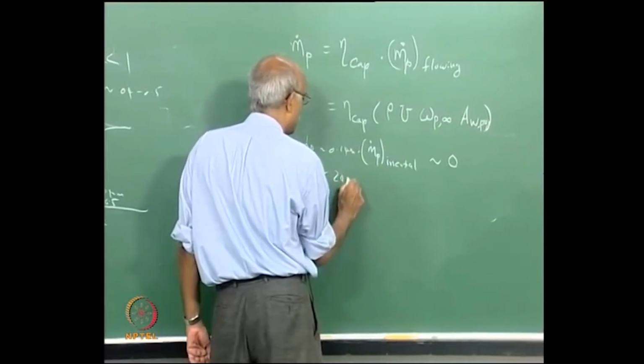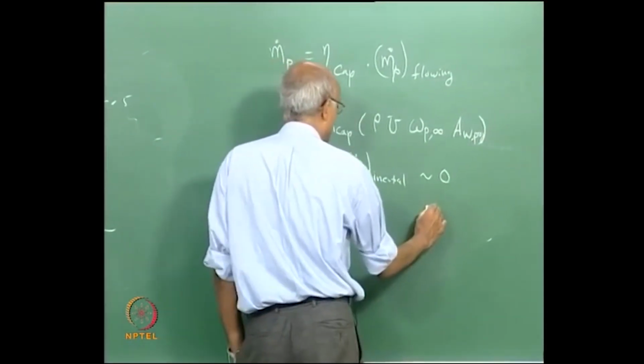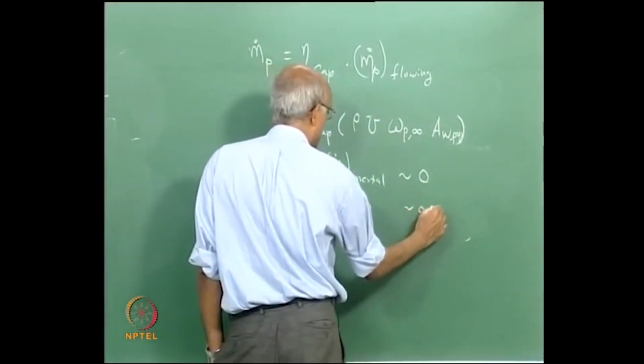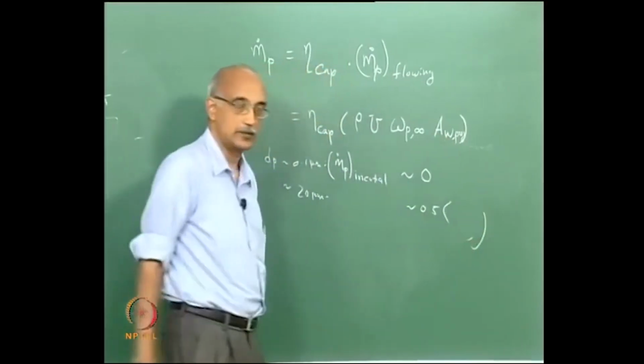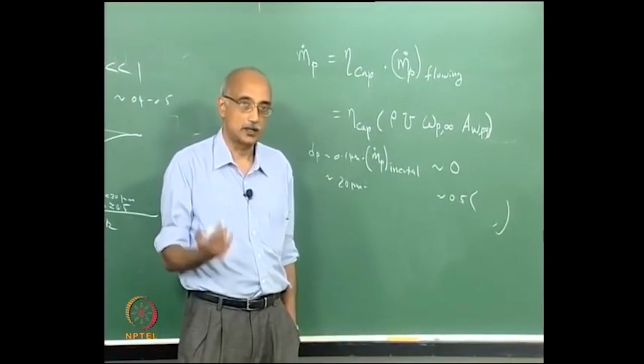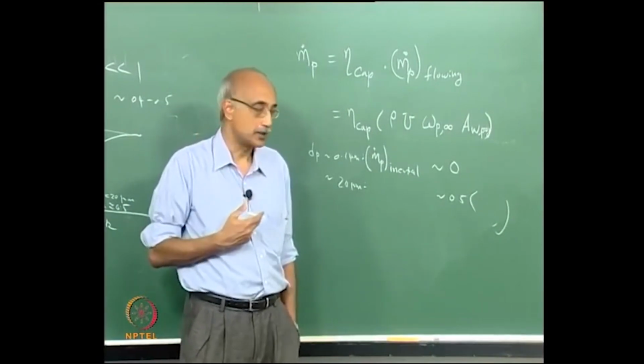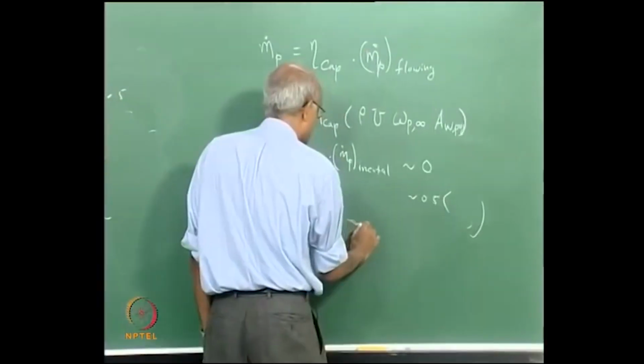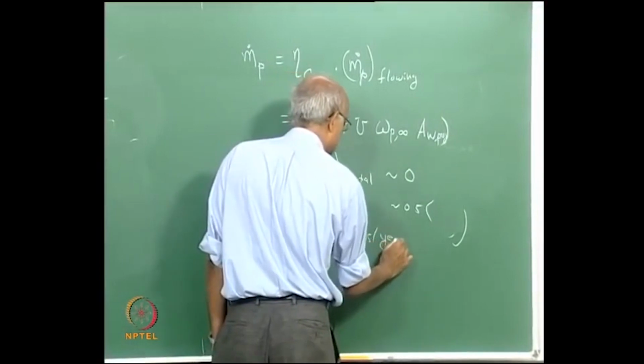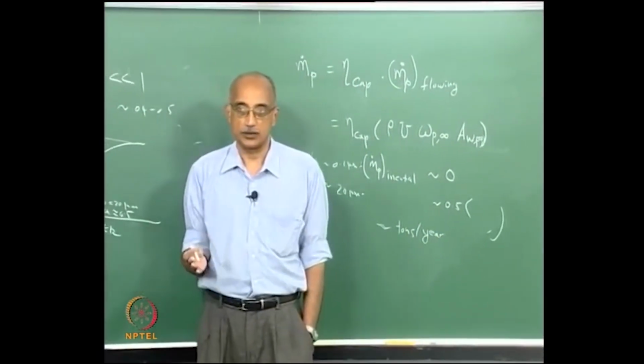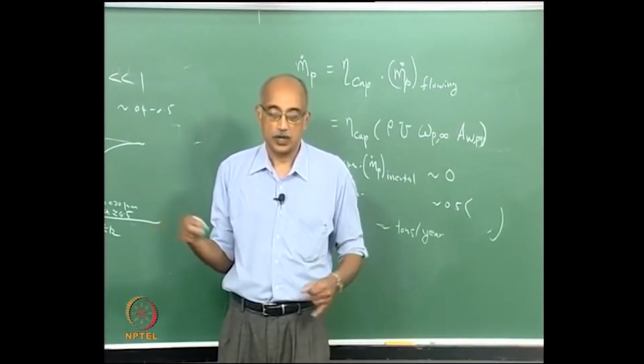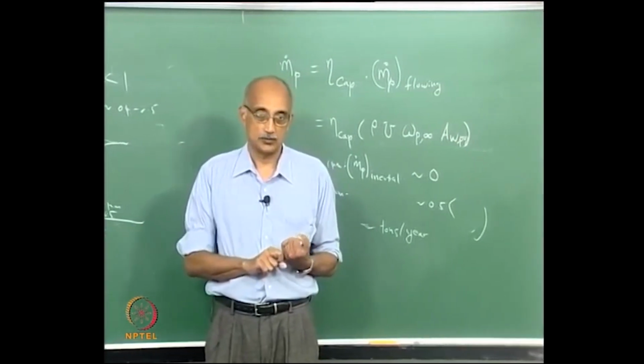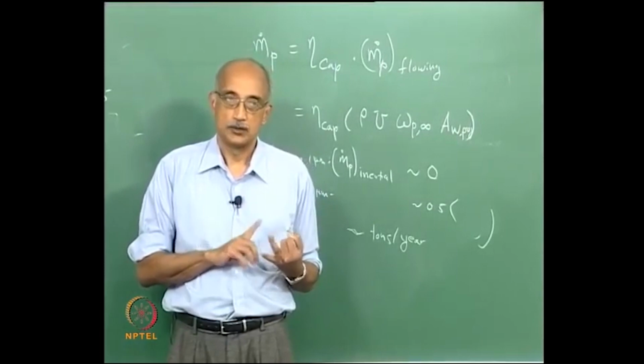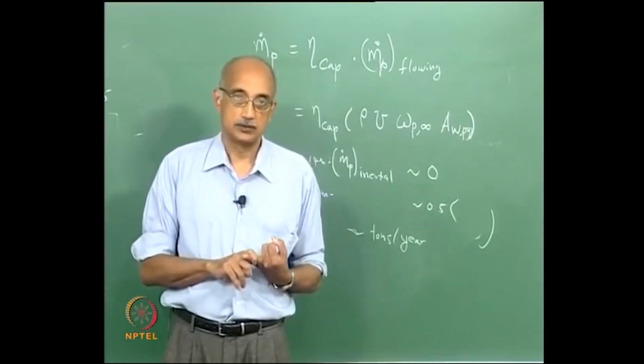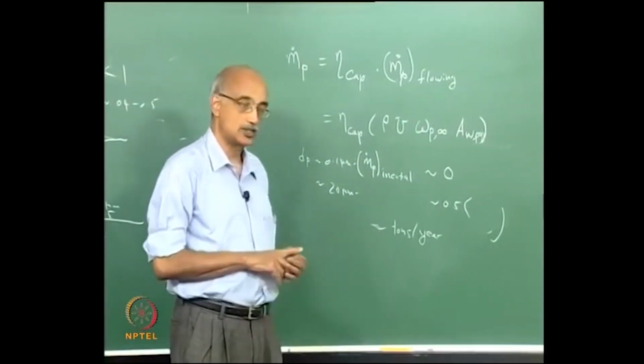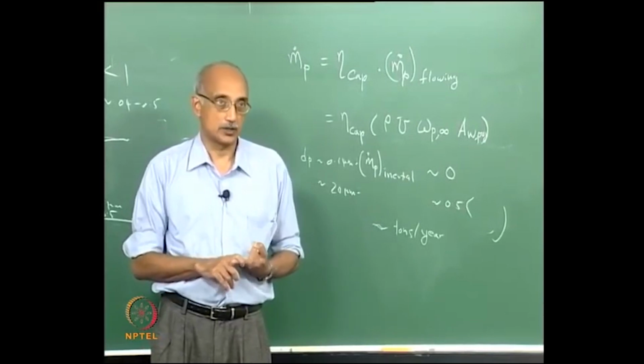Whereas for particles that are of the order of 20 microns, the same capture efficiency value, whether it's 0.5 times this number inside the parenthesis, and again if you do the calculation for a realistic set of power plant conditions, we finally obtain values that are of the order of tons per year when you include inertial effects into your calculations. So if you recall, we have gone from grams per year of deposition if you assumed perfect analogy between heat and mass transfer, to kilograms per year if you assume thermophoresis is important, to now estimating tons per year if you assume inertial effects are also important.